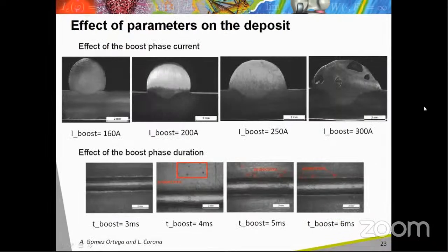One can see on this slide the effect of the variation of the boost phase current and duration on the deposit geometry for a steel. An increase of the boost current increases the volume and the temperature of the deposited metal, which creates a better wetting. However, an excessive boost current also creates a vaporization of the wire metal, resulting in a porous deposit. An increase of the pulse duration also increases the width of the deposit and improves the wetting. But, as described before, an excessive increase also produces sputters, observed in the white circle in the micrograph.